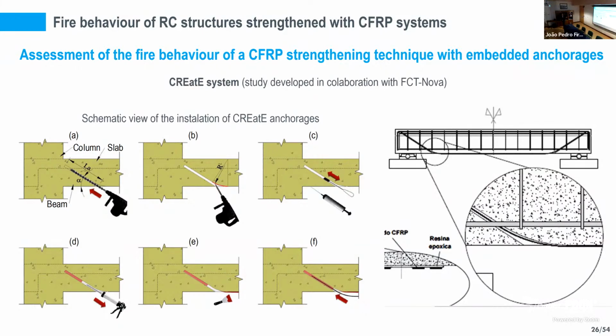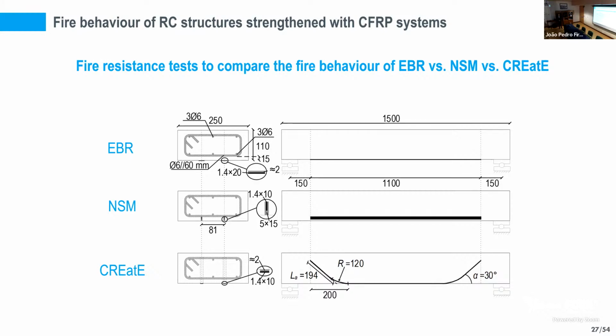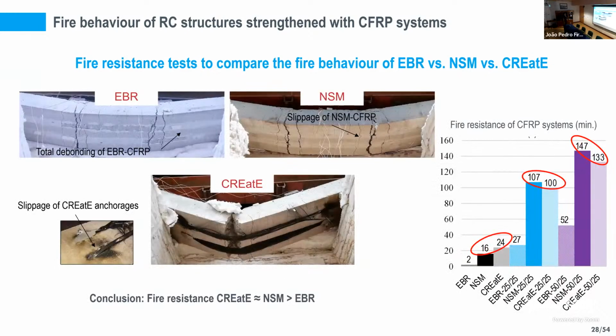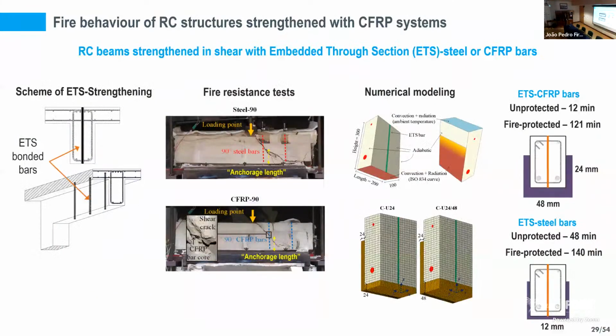So we assessed the fire behavior of the system, and for that we designed a new experimental campaign where we directly compare the fire behavior of the systems, also with the one that I mentioned before, the NSM, the CFRP laminates bonded inside the concrete cover, and we compare with the traditional technique where the CFRP are bonded at the surface. Well, the main conclusion of this study was that both this anchored system and the NSM system behave much better under fire than the traditional EBR system, and using that methodology for fire protection that I mentioned before, we again were able to attain fire resistance times that fulfill the requirements for typical building applications.